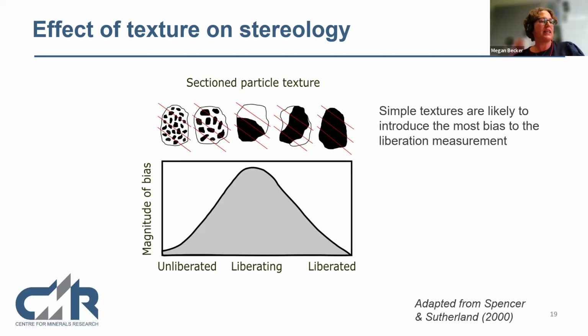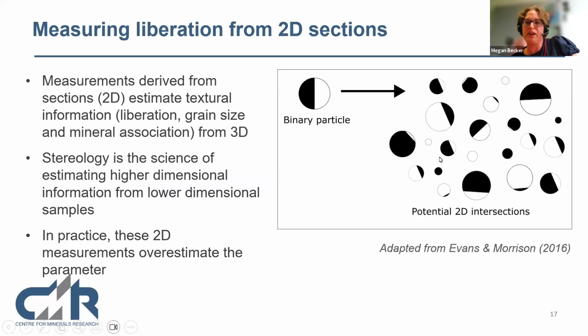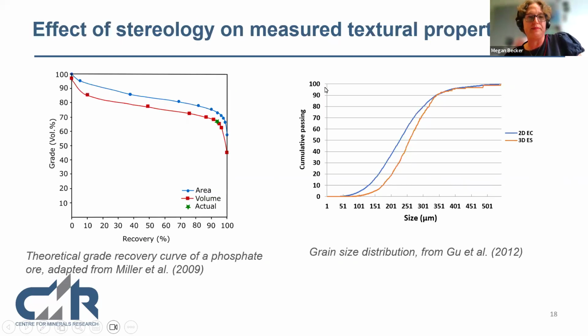So what do we do with this? I know that there were a number of studies in the last 20 years looking at stereological correction factors. They tend not to be used, even though we can apply them. People tend to just prefer to report the actual measurement, appreciating the stereological error. We also work with sized samples, and that also helps us minimize some of the error. And maybe if I just show you this quickly, if I use a size sample and I virtually remove all these tiny particles here, which could be like the apex of the egg, I'm essentially removing particles that are not giving a good representation of what that should be.